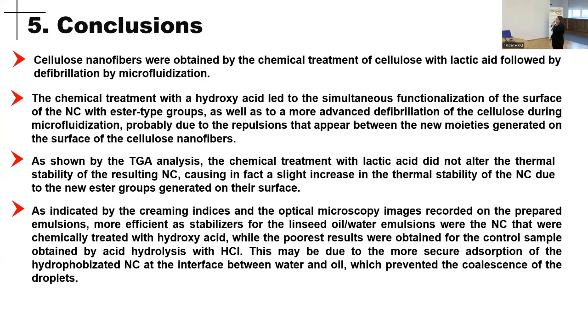In conclusion, we obtained chemically modified cellulose nanofibers by treatment with a weak acid, lactic acid, followed by microfluidization. We have seen that the chemical treatment with lactic acid led to the simultaneous esterification of cellulose with lactic acid, and also aided in the defibrillation of cellulose during the microfluidization step.